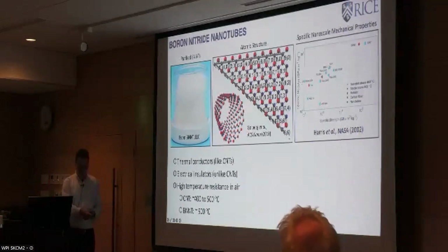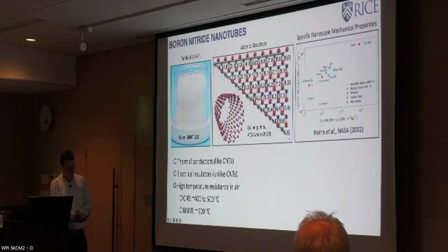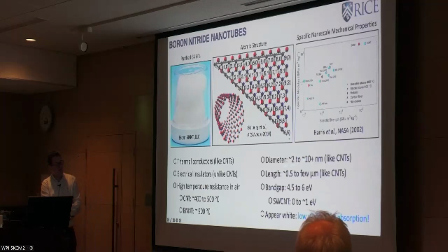I wouldn't say that carbon nanotubes burn easily. You gotta take them to about 500 C and keep them there for a while. Boron nitride nanotubes will not burn until about 900 C. But the other thing that's interesting is that geometrically, they're about the same as carbon nanotubes. Again, this is all polydispersed, and depending on how you synthesize, you get different average and breadth of the distribution. But the diameter is in the few nanometers. The length is between a fraction of a micron to a few microns, maybe tens of microns sometimes.